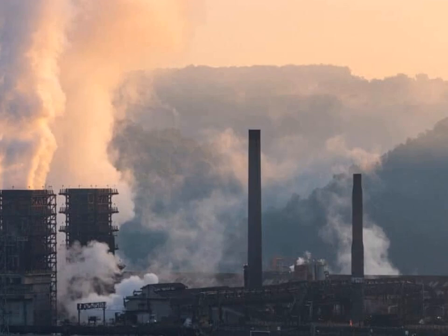Hold on, that seems backwards. If GGBFS has a higher footprint than fly ash, how does it lead to a bigger overall reduction in the concrete's emissions? That's a really important point, and it highlights the nuance here. The key is the percentage of replacement you can achieve. While GGBFS has a higher individual factor, you can typically replace a larger proportion of the Portland cement with it, say 40% or even more in some mixes, without negatively impacting the concrete's strength or durability too much. Fly ash is often limited to lower replacement levels, like that 25%.